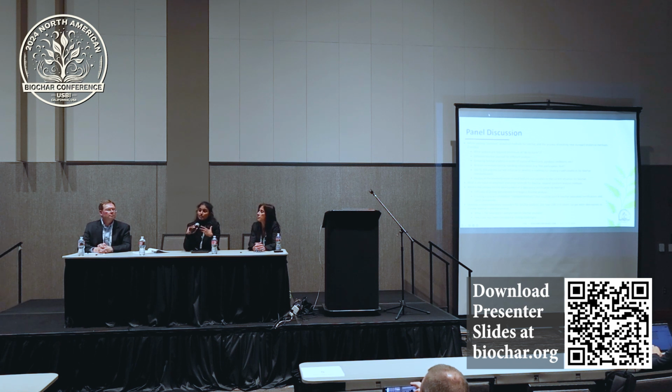So there are new ways of analysis coming to especially understand the bioremediation sector, because I think this is one of the least studied, because we are very much used to the adsorption kinetics of Langmuir and Freundlich models and do that and get the K constants. But if we have to do it in terms of the analysis, which biochar is good, what properties to correlate, we should consider hydrophobicity and electrical conductivity as two other parameters that need a correlation, other than the surface area and porosity.